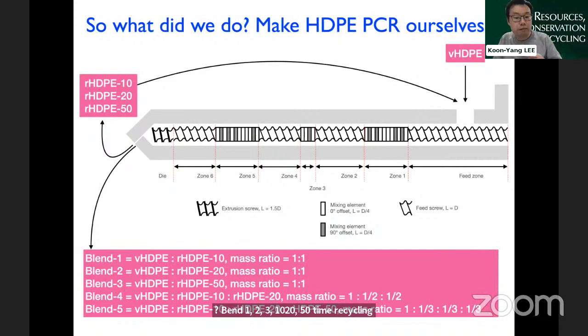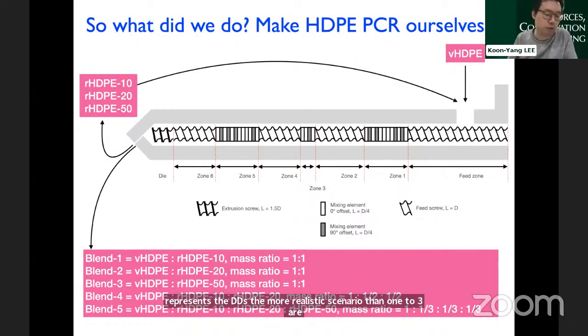Blend 4 and blend 5 are effectively virgin high density polyethylene mixed with polyethylene that are recycled 10 times and polyethylene that are recycled 20 times. That's blend 4, and blend 5 will be virgin polyethylene mixed with 10 times recycled polyethylene plus 20 times recycled polyethylene plus 50 times recycled polyethylene at the mass ratios given there. So blend 5 probably represents the more realistic scenario. Blend 1, 2, 3 are much more of the idealized worst case scenario, if you will.